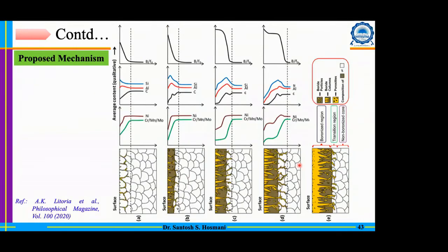Now we have refined our understanding of the mechanism, and we have proposed a matured mechanism here. We have correlated the migration of the elements with the nucleation and growth of this boride. You can see figures A to E, how this phenomenon happens during boronizing. Initially at the grain boundary there is boride formation, and it grows in a columnar fashion. During that, rejection of elements happens and changes the chemistry of the matrix. So you can see a grayish region here compared to the non-boronized core. Then finally, you have the simultaneous growth of the transition zone as well as the boride columns. That is how the layer matures.